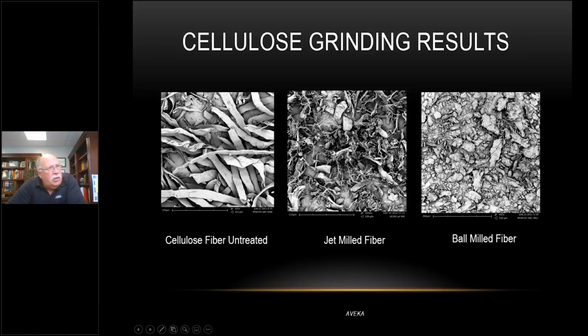But now if I took this ball milled fiber, it drops down to about 1. And you can kind of see it. There's not as much capillary opportunity here, and kind of push this all together. But now when we look at the water holding capacity of this jet milled fiber, it actually holds about 10 times the amount of weight.